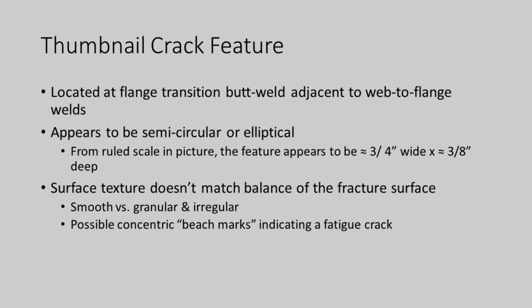And as we noted, the surface texture doesn't seem to match. The rest of it's irregular and grainy, and this is somewhat smooth, and we have these lines that a person could think would be beach marks. Not a lot to go on, but you run with what you got. So my failure analyst and I came to the mutual conclusion that's a defect.